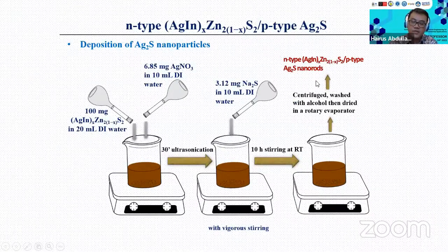Then the next step is because we want to combine with the p-type Ag2S. Then we take the powder of AgInZnS, just disperse in DI water, and then we add Ag nitrate as a precursor. Then the next step is we add sulfur source by using sodium sulfide. Then after 10 hours, just stirring at room temperature to make it uniform. So we take 10 hours to make all the Ag2S formation attach on the surface. Then finally, we wash and clean the powder, the precipitation.